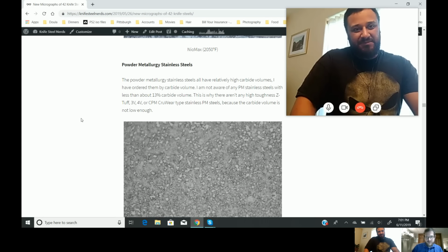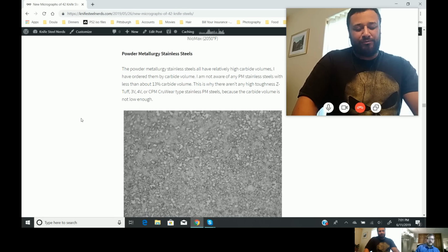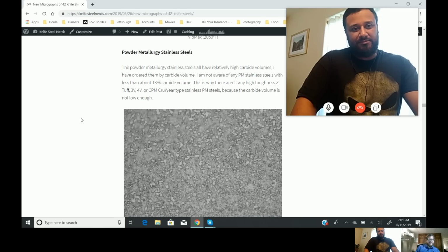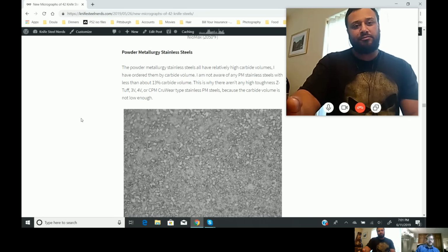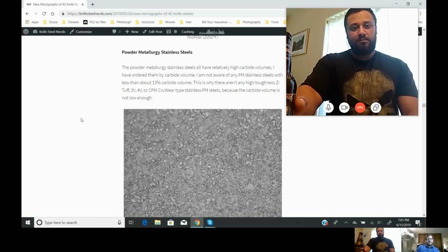Okay, now powder metallurgy stainless steels. So none of these have less than about 13 or 14% carbide volume. And that is significant because your really tough powder metallurgy steels, like your Z-Tuff 3V, 4V, they all have under 10% carbide. So that's a major limitation of the available powder metallurgy stainless steels. None of them are really high toughness.